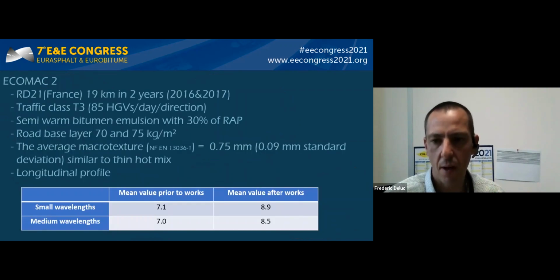The second process, known as ECOMAC Second, was laid over a 2-year period on 19 kilometer lengths of road on the RD 21 country road in France. The level of traffic of this pavement is 85 HGVs per day and per direction. The semi-warm mix contained 30% of RAP and was laid with a spread rate of between 70 and 75 kilograms per square meter. We observed that the mean macrotexture was 0.75 millimeter with a standard deviation of 0.09. These values are well able to stand comparison with conventional thin hot mixes, such as the French type A very thin asphalt concrete.